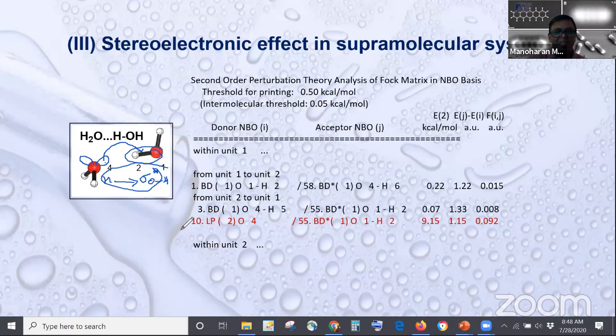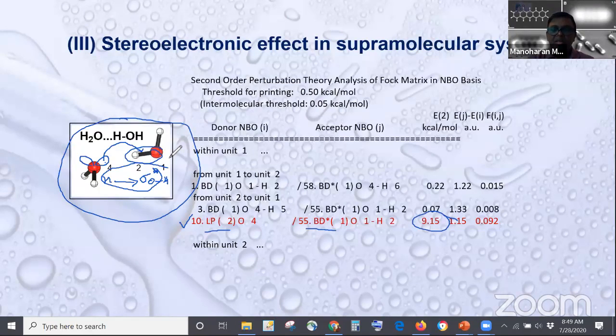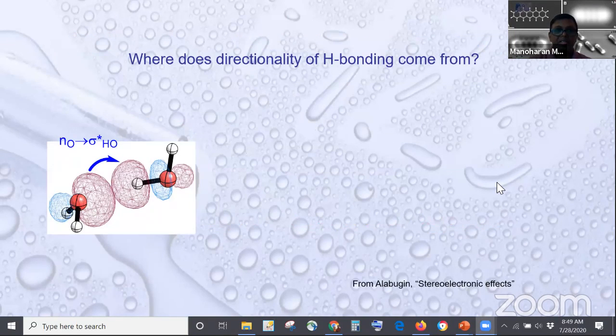When we collected the NBO data, you see that the lone pair to sigma star is roughly 9.5, or 9.15 kilocalories per mole, which is really huge. In kilojoules, that's even greater, times 4.184. So the hydrogen bond actually stabilizes the water dimer. That's how water is stable in the liquid form. Then think about ice. That's even more stable because you will see more hydrogen bonds in ice.